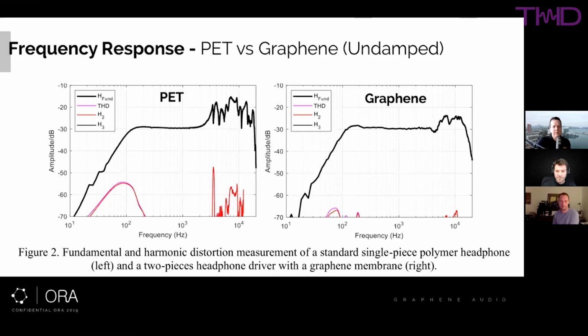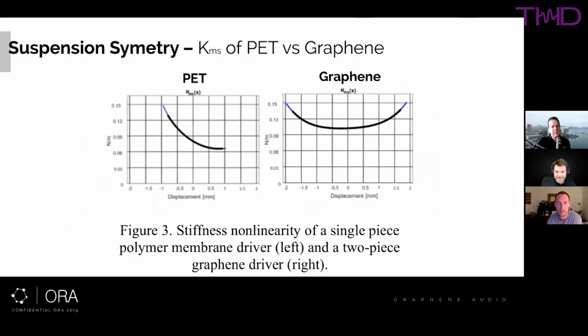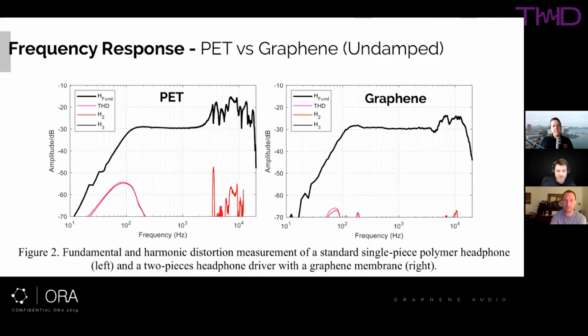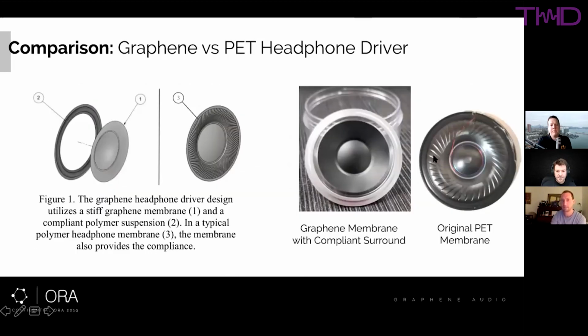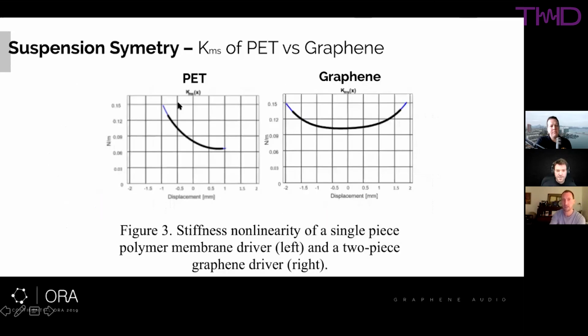Very cool. And there was another one there with stiffness, linearity. Oh, well, this I can't really take credit for. It's not the graphene that's doing this. It's the fact that we're using a free edge design. When you have a single piece where the membrane is the suspension, it's hard to get this linear KMS function over a broad range. So often what they do in headphones is dampen the headphone driver a lot, put it in this pressure chamber so that it doesn't have to move very far in order to produce bass.